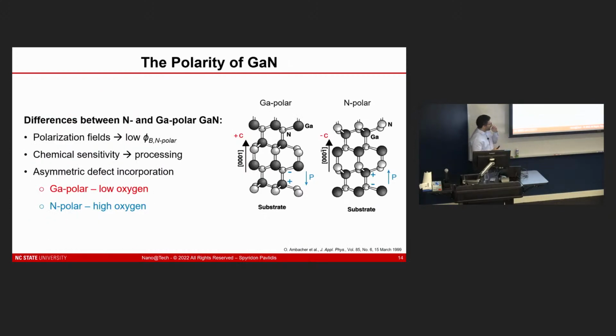So when we were all talking, and Zlatko and Ramon have been thinking about this for a long time as well, there was this idea of leveraging a unique property of gallium nitride, which is the fact that GaN is a polar material, and you can basically grow it either gallium polar or nitrogen polar, which, as you can see, comes about as a result of the differences in the direction of the polarization fields. And there are a few important consequences of thinking about gallium polar and nitrogen polar.